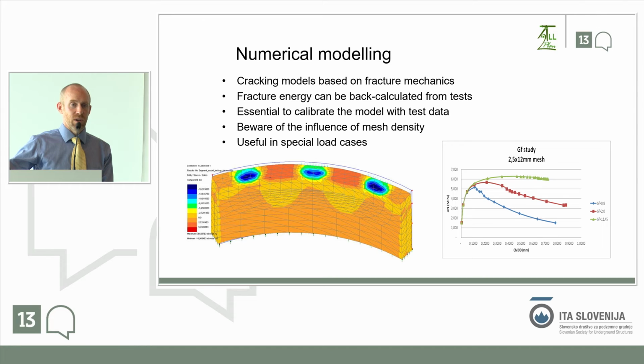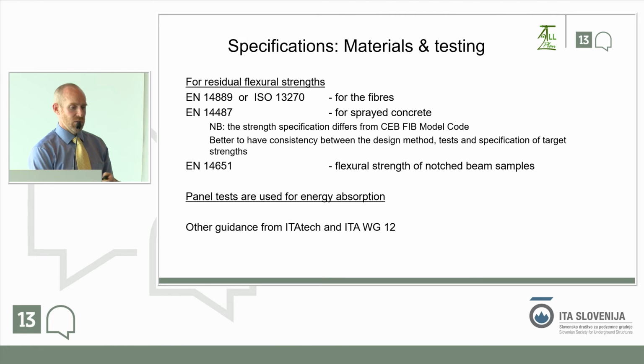So we can model these using sort of the fracture energy approach inside a typical sort of finite element, finite difference code. But here you have to calibrate your model based on the data you have. So you're looking at the energy, which is the area underneath the curve, this load deformation curve, and that's how you calculate the response of the concrete. So you can use that as a way to check your designs if you need it.